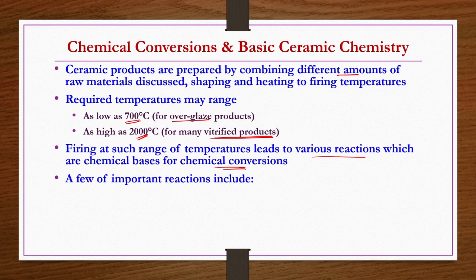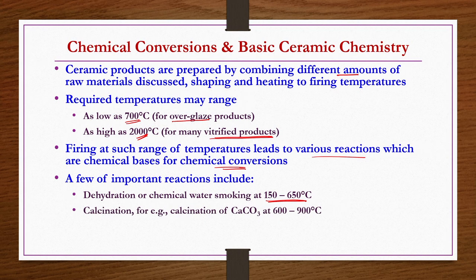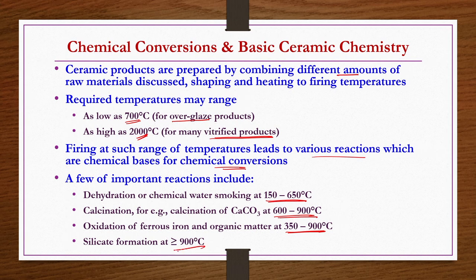A few important reactions include dehydration or chemical water smoking at 150 to 650 degrees centigrade. Then calcination, for example, calcination of calcium carbonate at 600 to 900 degrees centigrade. And then oxidation of ferrous iron and organic matter at 350 to 900 degrees centigrade. And then silicate formation beyond 900 degrees centigrade. Now you see, these are the generalized reactions. Not only these reactions, there may be a number of other reactions also possible. But categorically, these are the four important reactions that are possible in the basic ceramic industry when the ceramic product is produced.